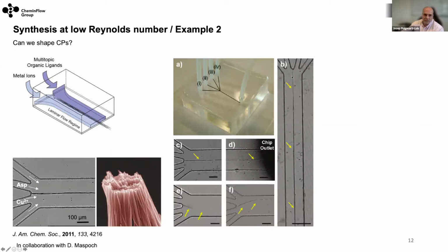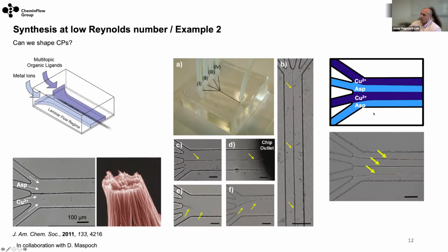Some people ask me, why is it that you have a wider bundle here? The answer I already gave before. It's because we are enabling these two regions to diffuse more and more downstream. So this is why here we have a thicker bundle of nanowires. But also note this here. If we change the flow rate in these positions, we can also guide the coordination pathway of this coordination polymer. And if we alternate the flows, we also have parallelization, so we can have a parallelized synthesis of this coordination polymer. We were quite surprised that we could generate these bundles of nanowires in 300 milliseconds.